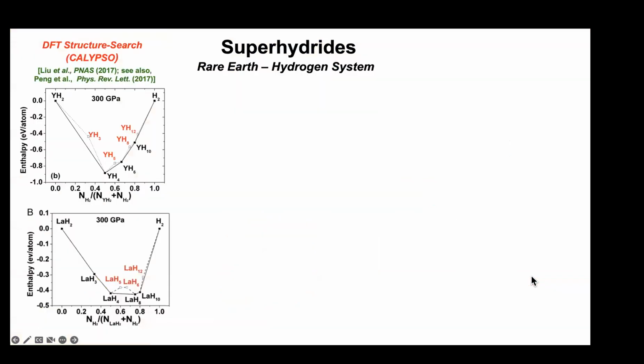We became interested in this problem ourselves and focused on the rare earth systems, thinking that the rare earths might be able to supply those extra electrons needed to destabilize the hydrogen molecules at high pressure and give you lower pressure stability of systems that could look like metallic hydrogen, and also perhaps with higher Tcs than those p-block elements. So here are some convex hull plots for yttrium-hydrogen and lanthanum-hydrogen. The work was done by Hanyu Liu in our group.